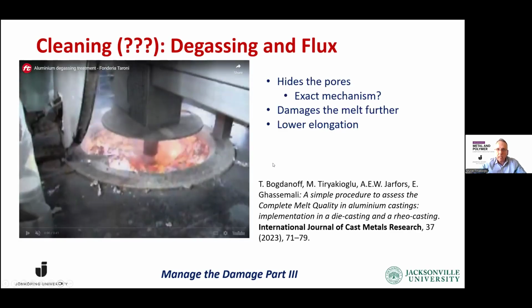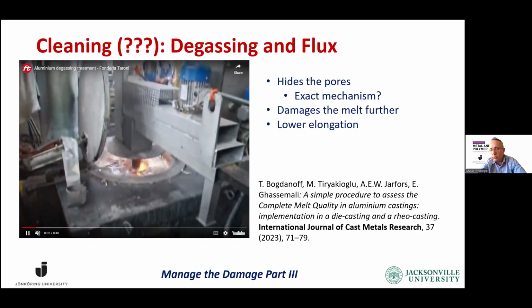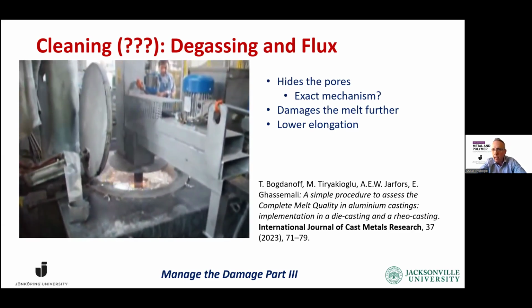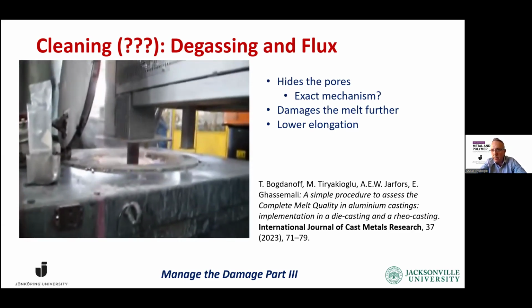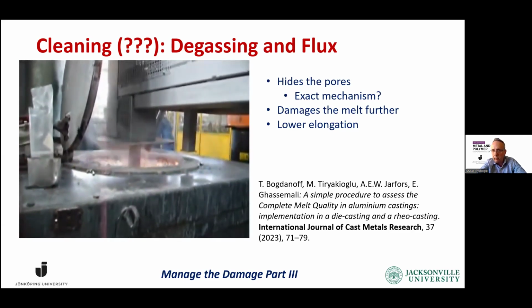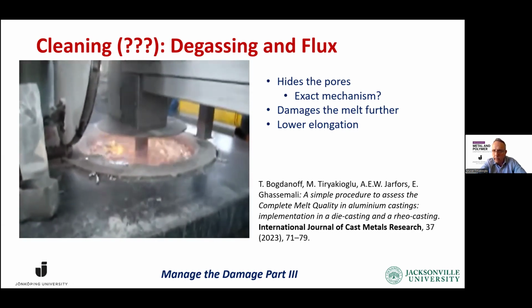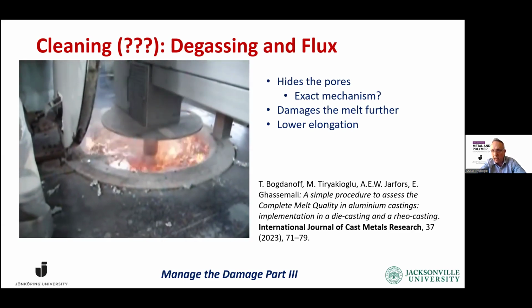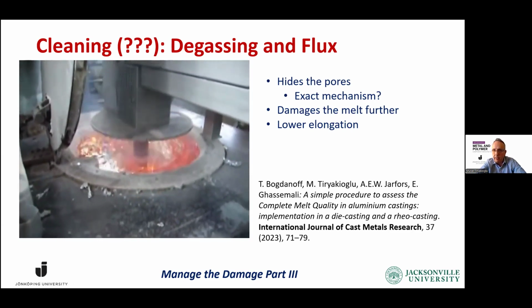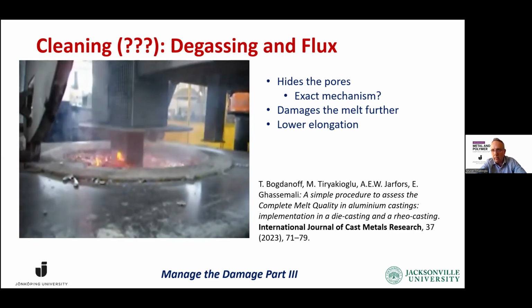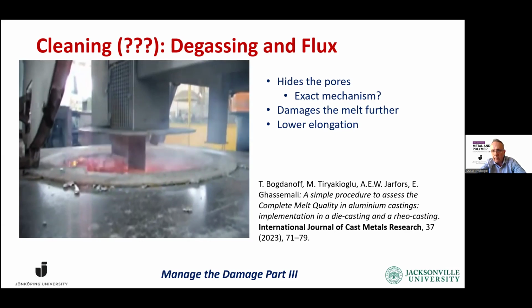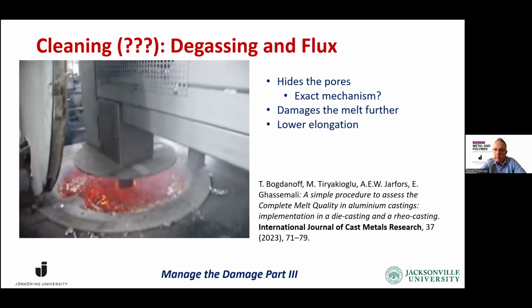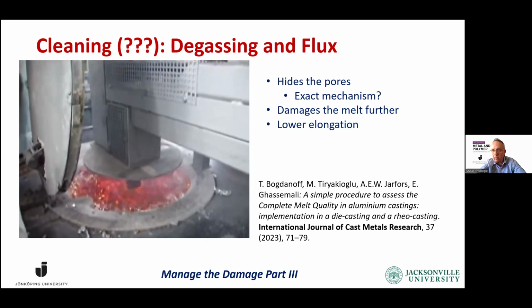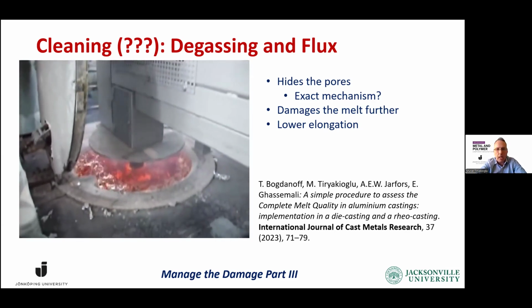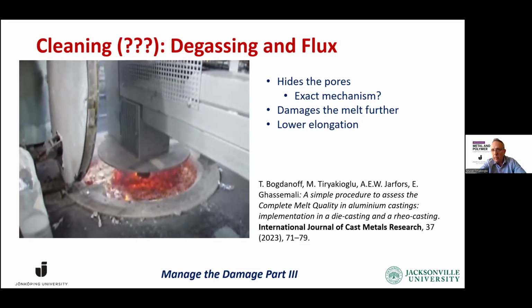It's an excellent way to hide the pores, and it's been designed to hide the pores. At this point, we don't know the exact mechanism of how it hides the pores, but it does. But one thing that we have found out is that it damages the melt further, and it gives much lower elongation, which we reported in our recent paper that you can read if you want to, because we followed the damage in 2 foundries and found that it's consistent after this operation. Yes, the pores are eliminated, but the metal is much less ductile.